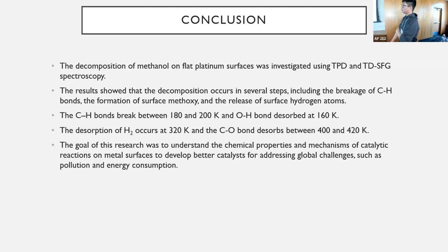The OH bond will break first when it is on platinum, and after that the 3 CH bonds, and then the CO bond will desorb between 400 and 420. We don't know yet if it's going to break or not, since the SFG and TPD don't provide enough data for that. And the atomic hydrogen on the surface will then form H2 and desorb around 320 K.